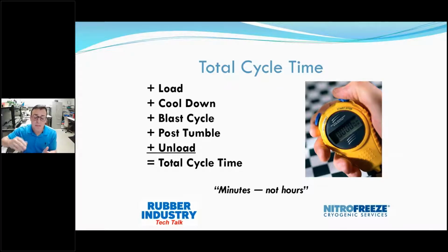Parameter. And what that is basically when you open that door, although it's a gaseous nitrogen atmosphere, the temperature will start to go back up to room temperature. So we try to keep that door closed when we're putting the basket in and do it very quickly. So you have to cool down.